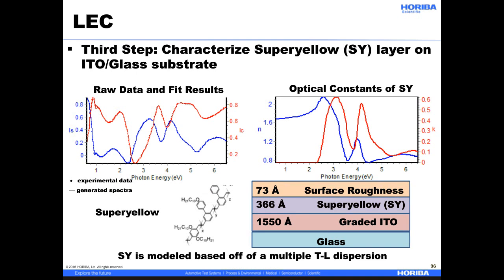The third step here is to characterize super yellow, since we don't know much about super yellow optically. The super yellow here is on top of the graded ITO, which is on top of the glass. On the left, you see the raw data from ellipsometry and the fit results. On the right, the optical constants of super yellow.